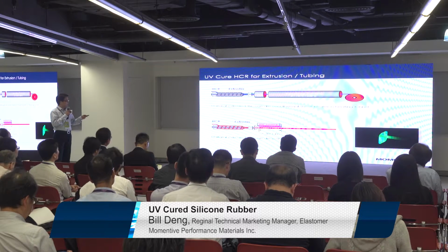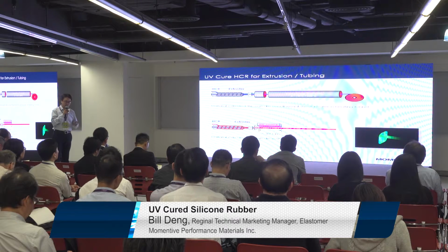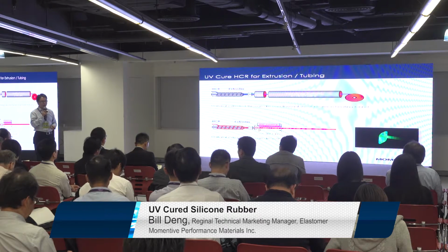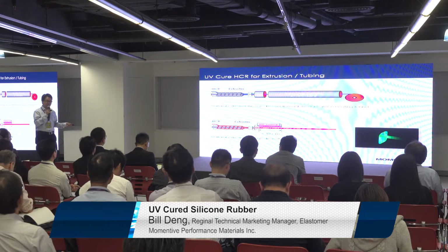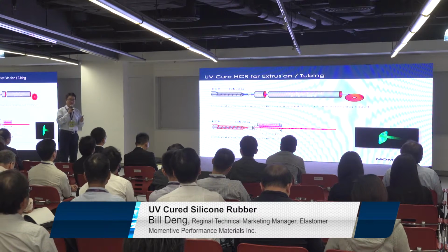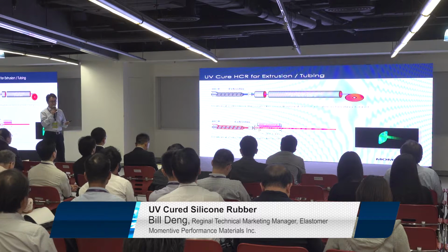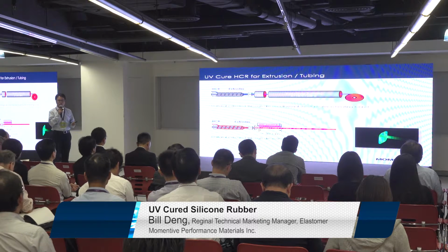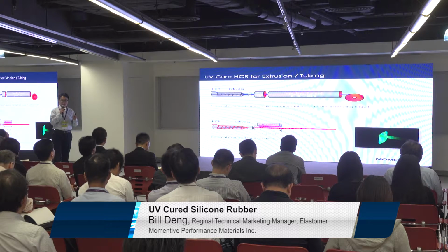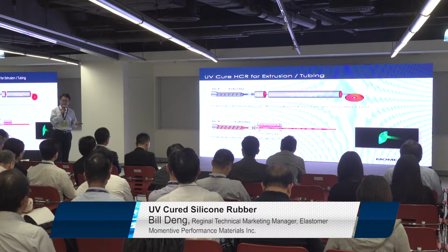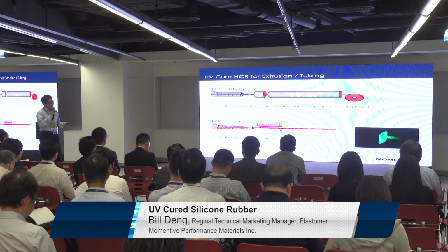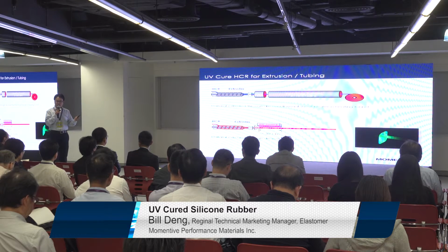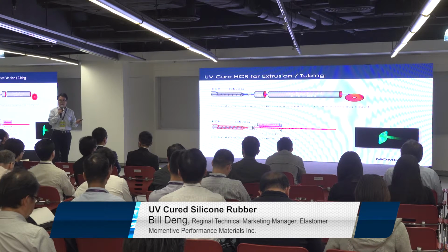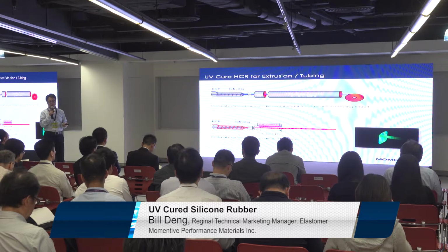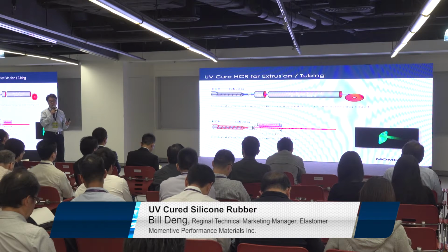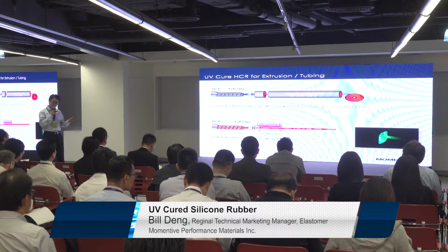So you can see it requires really high energy, because all the temperatures are very high. At the same time, if someone runs the extruder, they will see the most difficult thing is the bubbles in the silicone rubber, because of the high temperature. First, if the silicone rubber contains some moisture, the moisture will become vapor and generate bubbles. Second, if it is cured by an addition cure system, it contains cross-linker. The cross-linker will decompose into some low volatiles and generate bubbles.